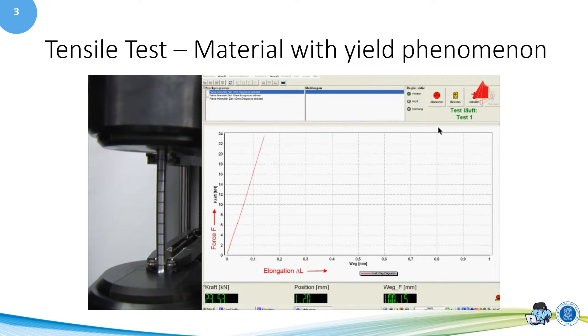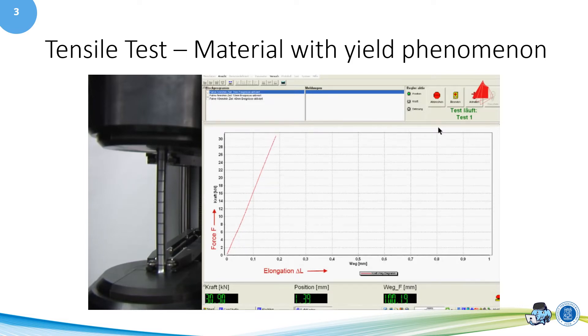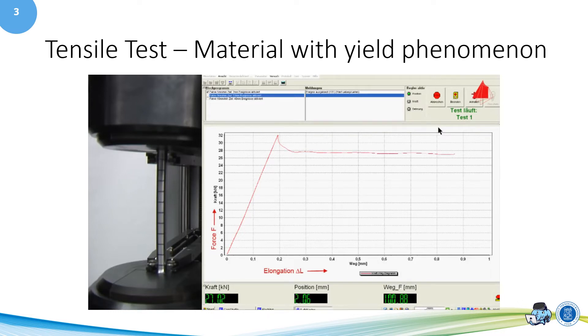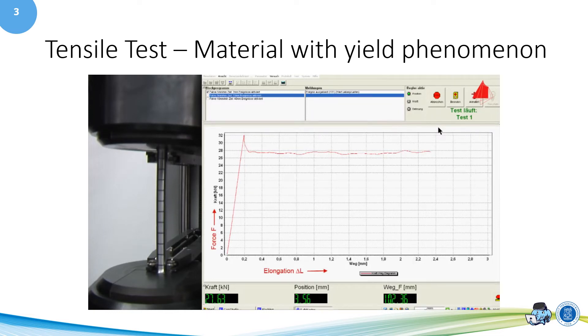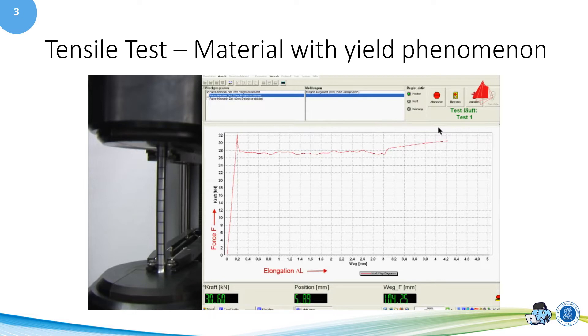In materials with yield point phenomenon, the end of the elastic area can be seen clearly. The plastic deformation starts abruptly and is accompanied by a sudden drop of force. If the test piece were to be unloaded now, it would not spring back to the original length, but instead show a permanent elongation. In the next stage of the tensile test, an almost constant force level with slight fluctuations occurs. This phenomenon is called the Lüders effect. After a certain strain, known as the Lüders strain, the force increases again. The material opposes an increasing force against the imposed elongation — it strain hardens.